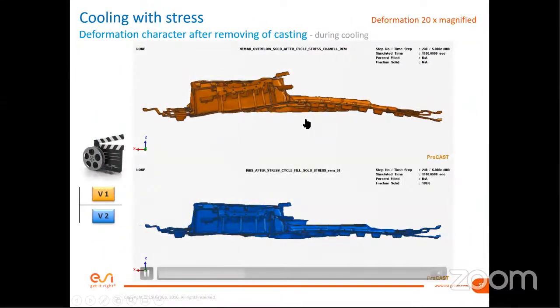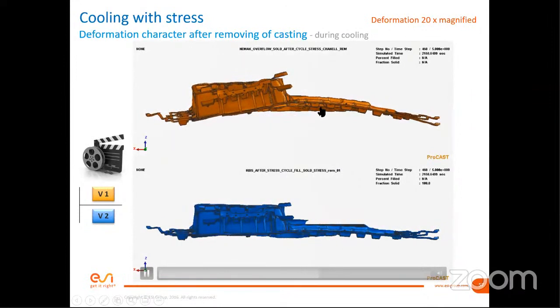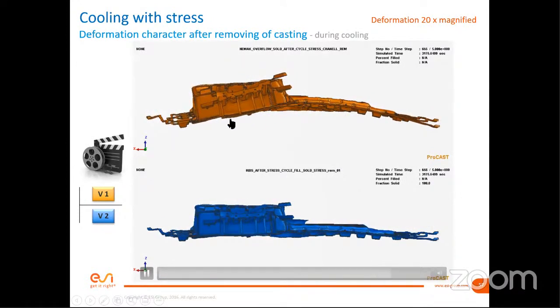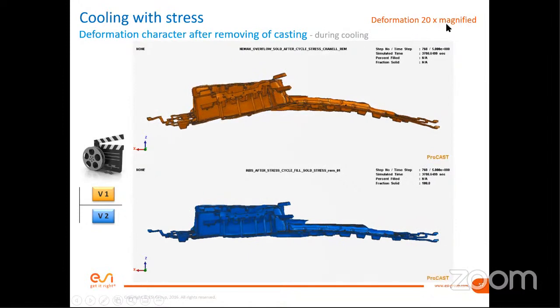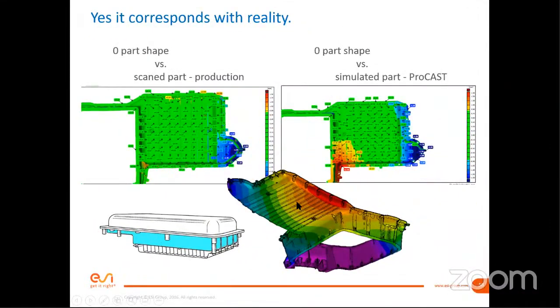If we check the situation from another view, you can see the bending effect, which is enormous here. Of course, this is not the bending of the real casting, it's 20 times magnified, because it's not so visible just by the eye, but it's visible here. And of course, with the bending like this, there is no way to assemble this part of the battery with the second part of the cover. So the problem was to have this bending. It was really not acceptable.